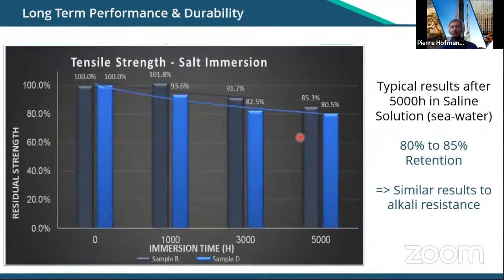For reference, this is not in the code or in any standard, but we ran the same test by dipping the bar into saline solution. Very useful to simulate marine application. And you can see in that case, the GFRP bar from Dextra sample B was pretty similar to the competition here, 80, 85. So I would say the chloride and the saline water solution, typical effect on the bar would be similar to alkali or even slightly less. So this is not a concern. Using GFRP also for saline application, coastal area, this is particularly applicable.